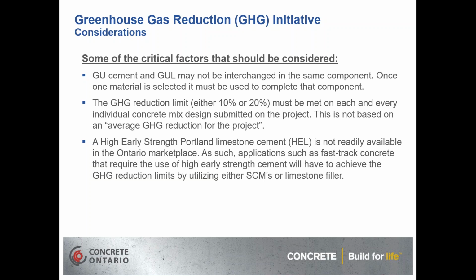Another consideration, that greenhouse gas reduction limit, be it the 10% or the 20% target, must be met on each and every individual concrete mix design submitted on the project. It's not being based on the average greenhouse gas reduction for the entire project. Every single mix has to meet it. So you can't, for instance, do half of your concrete at 20% and half at 0% and have it count as 10%. Each mix has to meet that 10% or 20% reduction minimum.